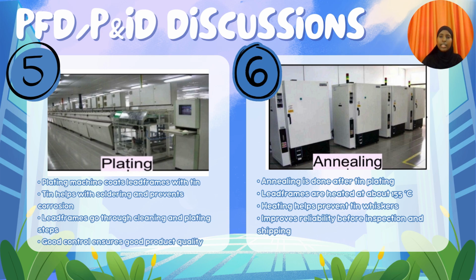So the next stage is annealing. In the annealing process, the lead frames are heated to about 155 degrees Celsius after plating. This heating process reduces internal stress and also helps prevent tin whisker formation. Annealing improves the reliability of the final product.